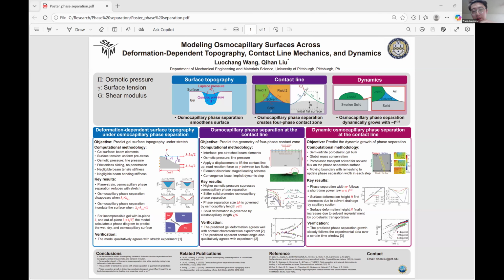In the initial part, the solvent exudes at this contact line, and as time goes by, it saturates because the surface is filled with this phase separation. So there's not so much motion from the bulk towards this surface. That's saturation, so that's why we have a plateau here. Yeah. Okay. Thank you very much.